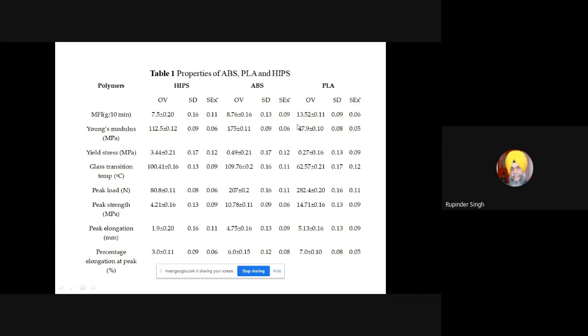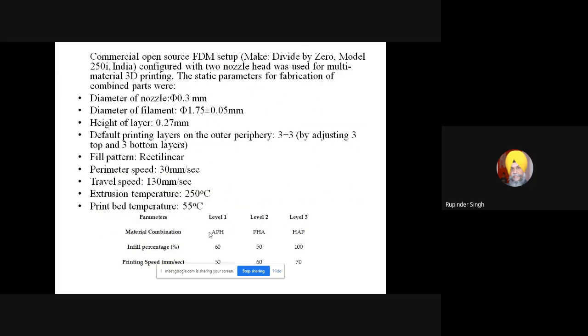Now, similarly, if you see the Young's modulus of the materials, for HIPS it was 112, for ABS it was 175, and for PLA it was 47. Then there is a difference in the yield stress, in the glass transition, and in the peak load and peak strength. These types of mechanical properties were all different for these three materials. So we try to see how they behave on a 3D printer.